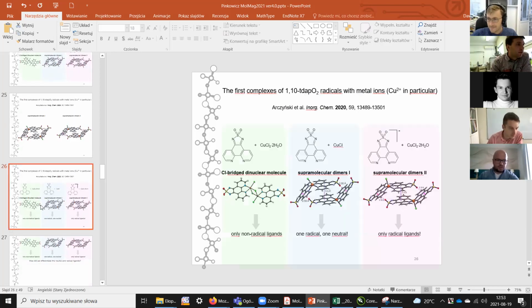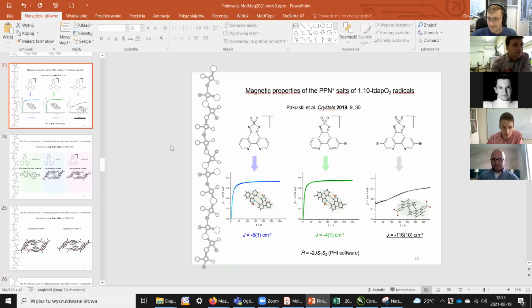Yes, 23, sorry. The last radical, you have a chi T value at low temperatures close to 0.18. That's right. It seems that only half of the radicals disappeared in your system, not all of them. We explained that in the paper. There are 2 types of dimers in this compound, strongly coupled and weakly coupled. One pair is weakly coupled, the other one is strongly coupled. And again, this is probably due to the pi stacking offset. Okay, thank you.